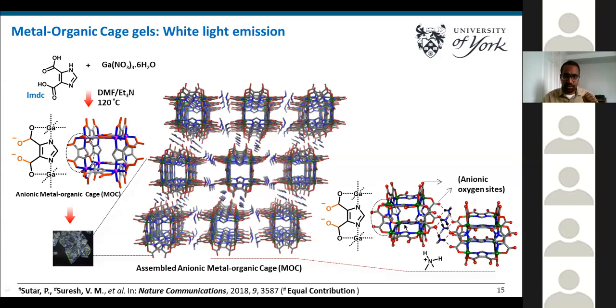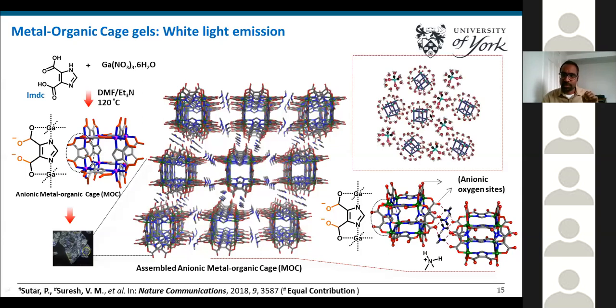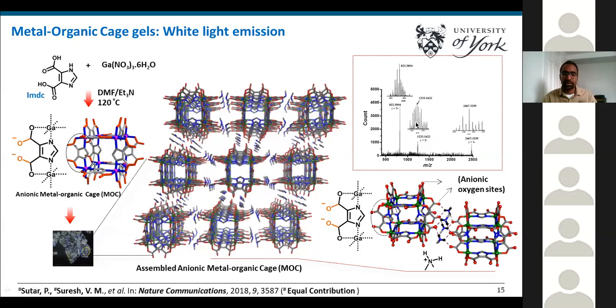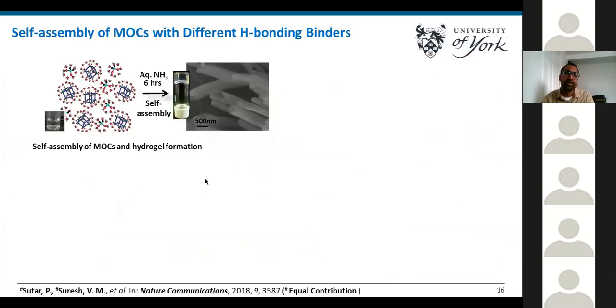Since this metal organic cage is extremely negatively charged, it is quite soluble in water. And the stability of MOC in water is also evident from high resolution mass analysis, where we see 3 different peaks for metal organic cages solvated by water with 3 different charges. So now we have a solution of MOC. We wanted to test its assembly with different hydrogen bonding donor systems. Now we started with aqueous ammonia, which is a strongly hydrogen bonding molecular binder.